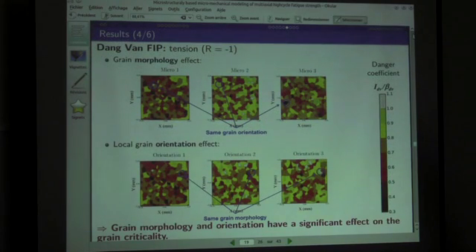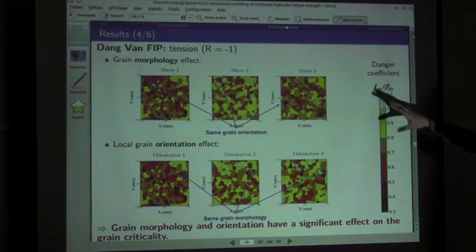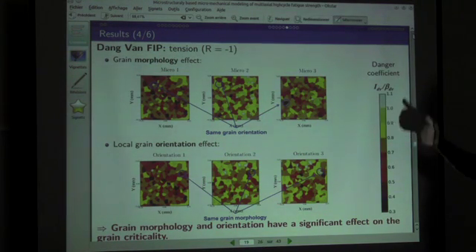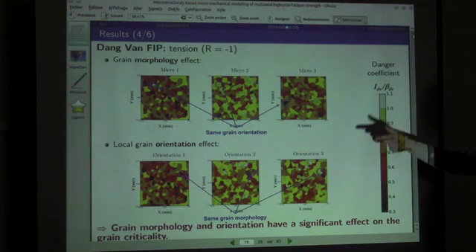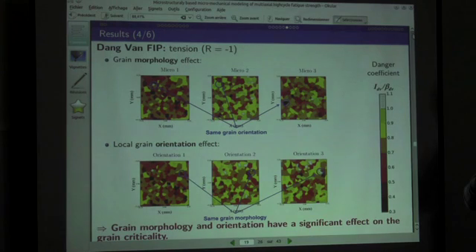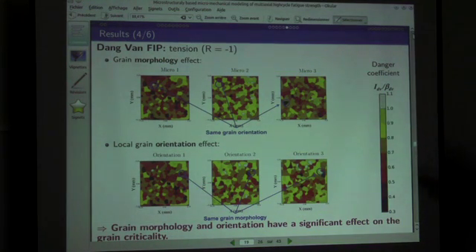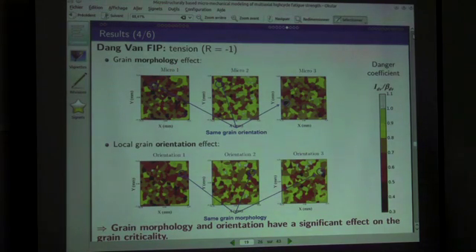Another remark that we have is that the microstructure depends on different parameters, which are morphology and texture. I don't want to go too much into detail, but we observe that granular morphology has a strong effect on the local stress strain. But the texture also has an effect, and the surrounding of the materials also has an effect. So it's a combination of geometry, texture, and neighboring effect. So all those parameters do influence strongly the local response in the aggregate. So that's also some consideration that we have to take into account when we are doing some comparison between experimental results and numerical results at these scales.